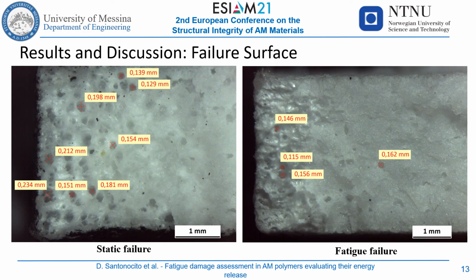Fatigue fracture surfaces show a smoother profile, typical of a brittle failure. Defects due to the lack of powder melting, with an average diameter equal to that of the static cases, have been found. The circular defects can act as initiation sites for plastic deformation that would lead the specimen to failure, both under static and fatigue loads.